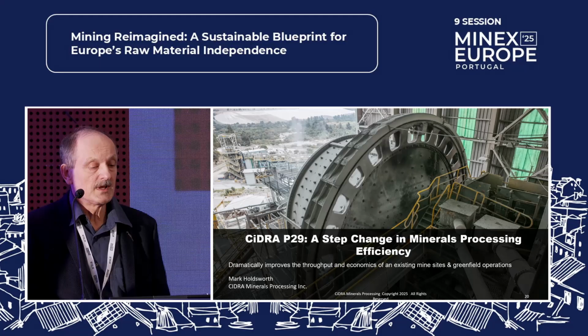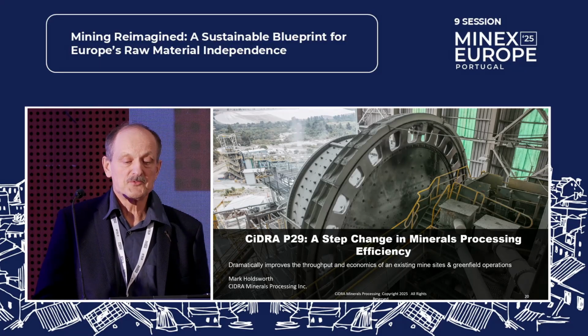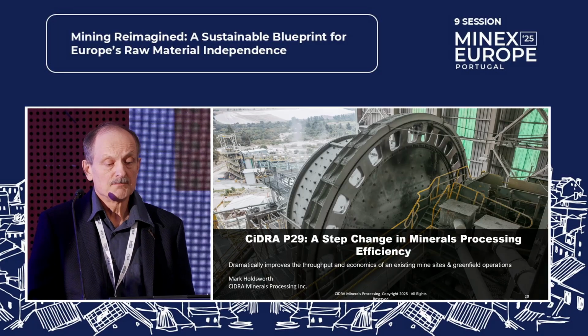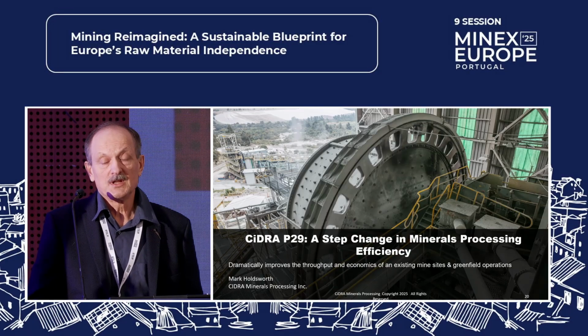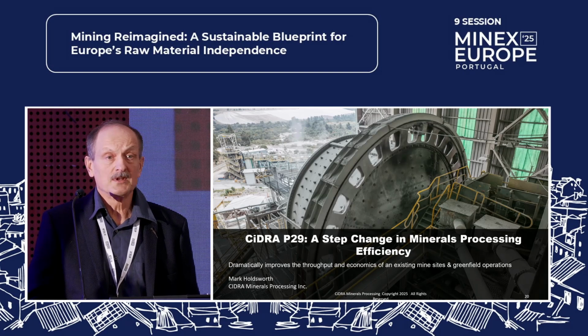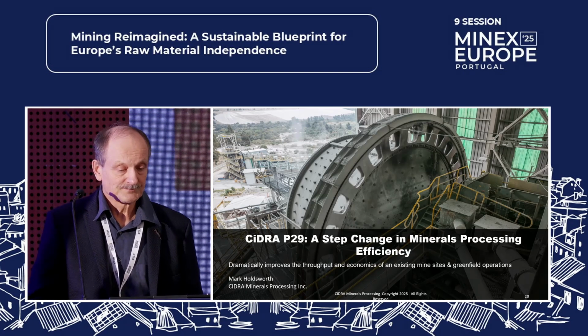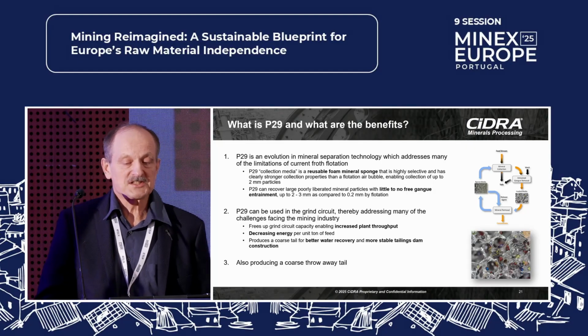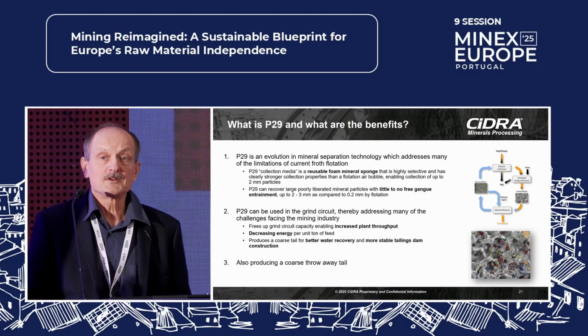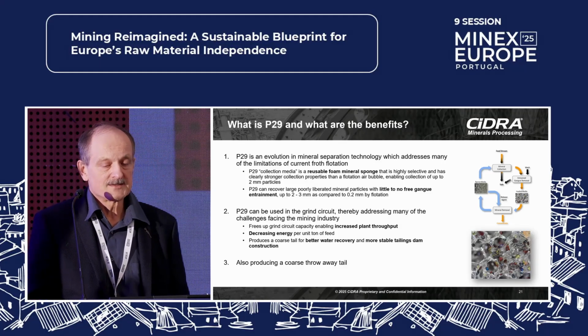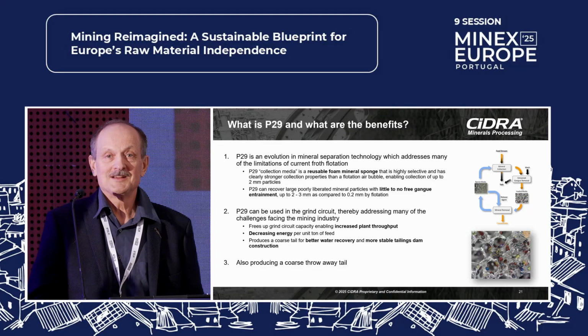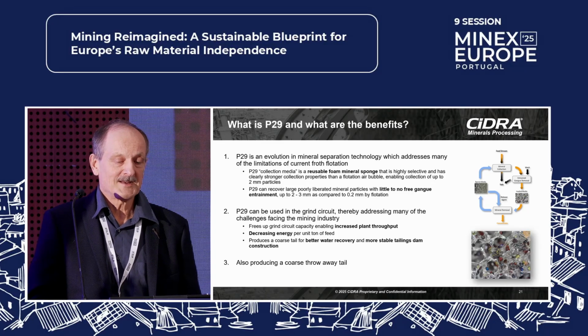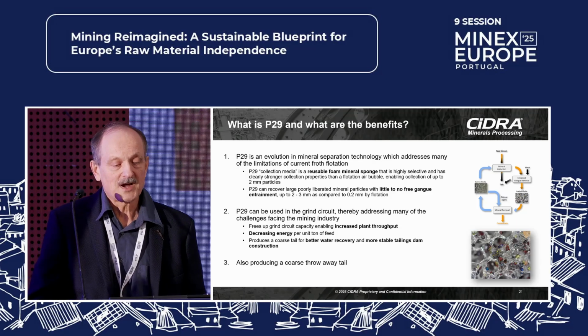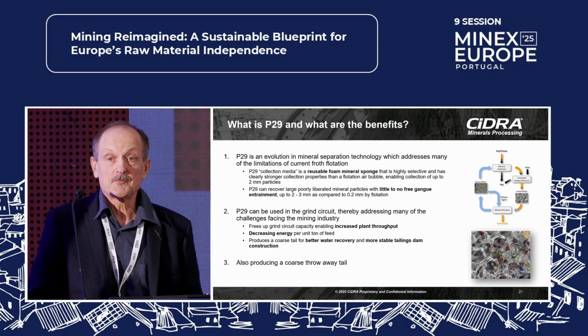Now we are introducing the P29, which is quite a step change in minerals processing efficiency, because that's a separation technology where, instead of bubbles used in flotation, we are using sponges. We just mix the sponges that are covered with the same flotation chemicals and put them into a drum with the ore, rotate that drum and capture the wanted particles there. We can do efficient separation up to 2 to 3 millimeter particles.